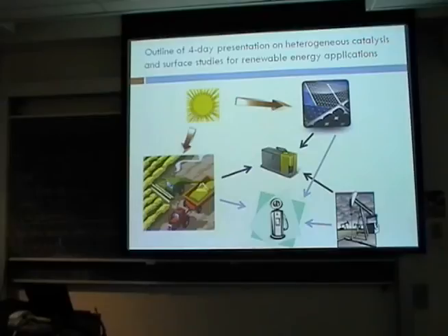Right, but could the reactivity do something with shifting these energy levels in a way that you could tailor? Oh yes, that's certainly a good point. You can affect the density of states at the surface and the relative band position. That can be important when you generate the electron-hole pair: to keep them from recombining, you want a downhill energy landscape for the electrons all the way to the products, which is really the key aspect of the reaction. So it could be that nanoscale features play a role in making sure it's downhill to the surface in terms of the band positions.